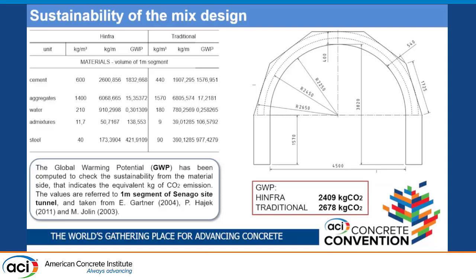So if you see, the density of concrete is 600, so it's quite larger than the traditional one, and of course the global warming potential, that is the equivalent kilograms of CO2 of emission, is larger, but not so much because of the presence of the CSA inside the binder of the Hinfra mixed design. But the very big difference is on the steel. So, for example, the Hinfra technology has 40 kg per cubic meter of steel fibers, whereas the steel reinforcement here is 90. I will go through this value in the next slide. So if we sum up all the values of the GWP, we can see that Hinfra has a reduced value.